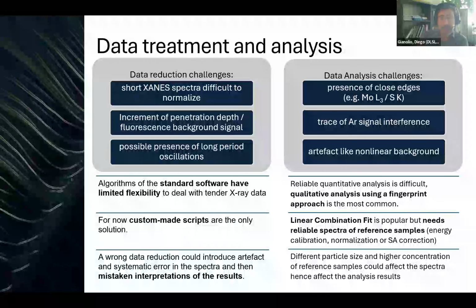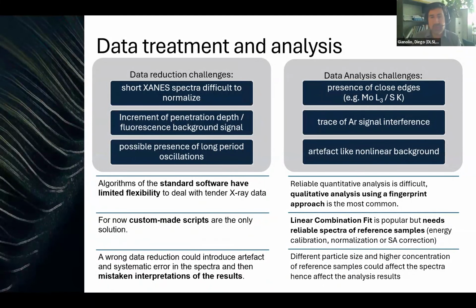When talking about the analysis, the problem of having multiple edges becomes, of course, very important because, again, it shortens the range and doesn't allow a good Fourier transform, for example, for the XAFS. There are also other interferences that could be coming from gas left in the chamber, for example, argon. And there could be artifacts that are introduced by nonlinear backgrounds that could be coming from the fluorescence or the total electron yield, for example.